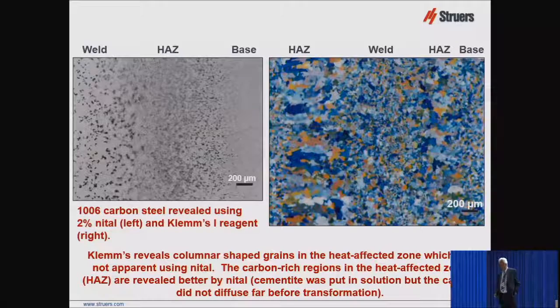And you notice in this zone over here, when you look at it in color, you can see columnar grains there. And that area was in the two-phase region of ferrite and austenite. And since it's columnar, that tells me that this steel was not aluminum killed. Because if it was aluminum killed, it would have stayed more equiaxed. But when it's non-aluminum killed and you're in the two-phase region, you're going to see columnar grains.